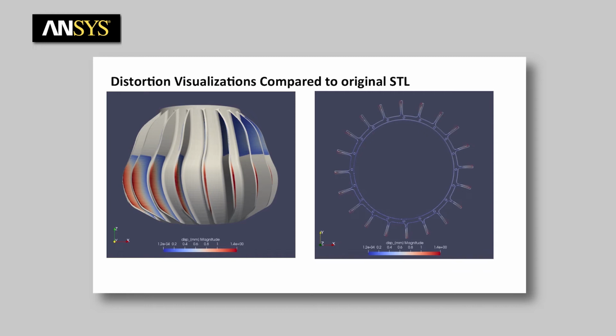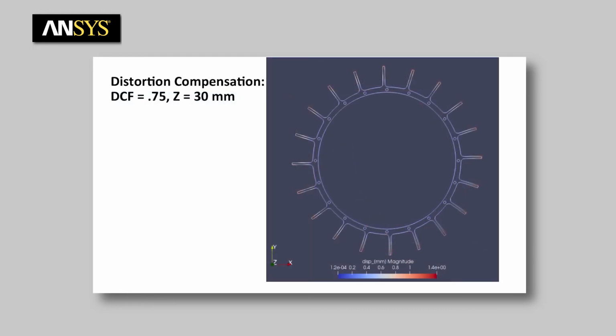that's how it built. So we went in and did a simple distortion compensation where we reversed the distortion by a factor of 0.75. So that means that if it was going to distort 1 millimeter this way, we went the opposite direction at 0.75 millimeters. And what you find is that in general, for most materials you reverse the distortion somewhere around 75 to 85%. And that's going to get you, when it redistorts, about the right level of distortion.